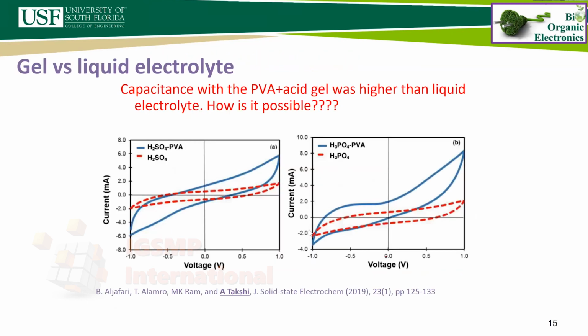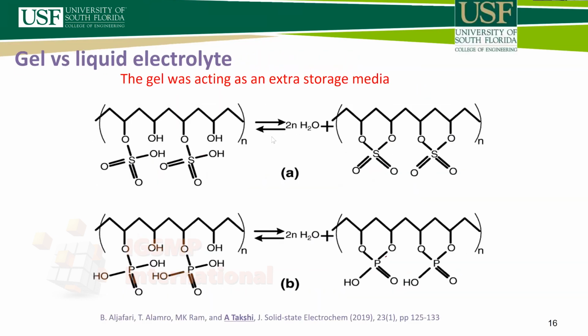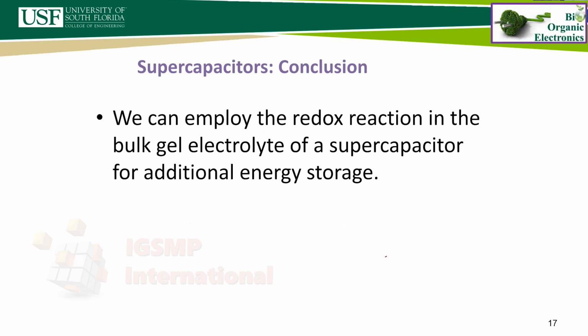And we did so, and we learned that the polyvinyl alcohol and the anions in the electrolyte can experience some sort of change in the redox state, which serves like a pseudo-capacitive effect, but not on the electrodes, on the electrolytes. So just to conclude this section, we were very happy to see that we can use the volume of the gel as sort of the extra room for storage in a supercapacitor design when we are employing what we call the redox active electrolyte.